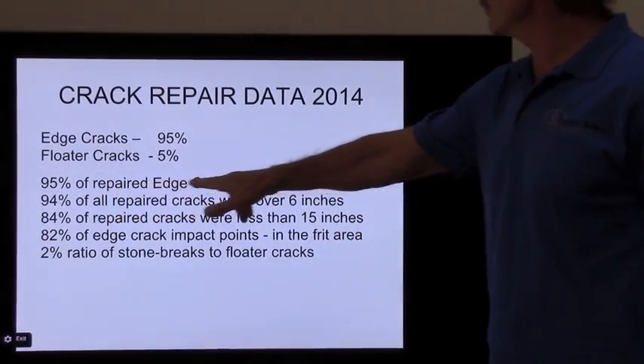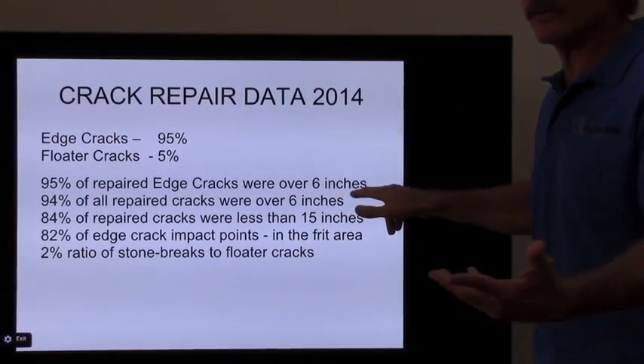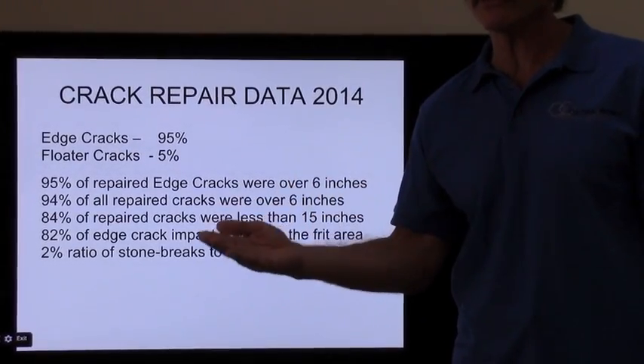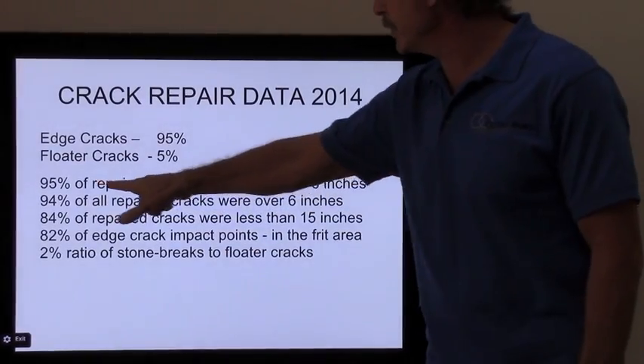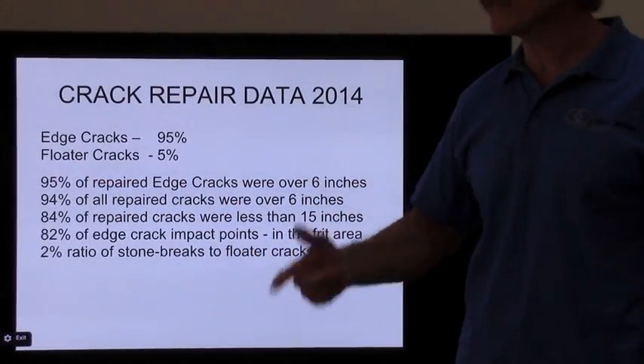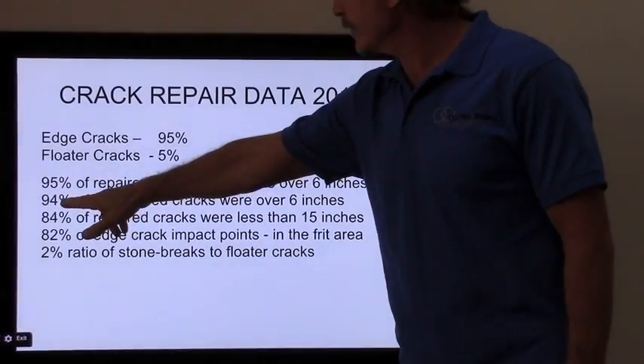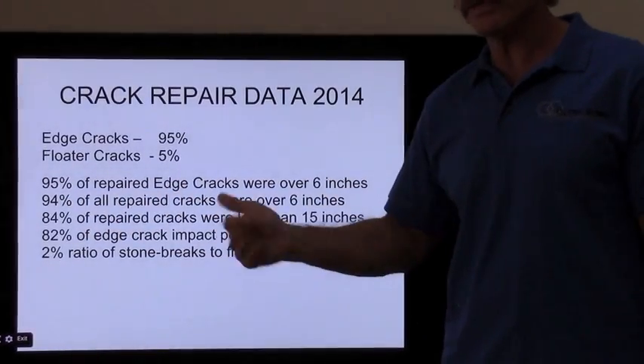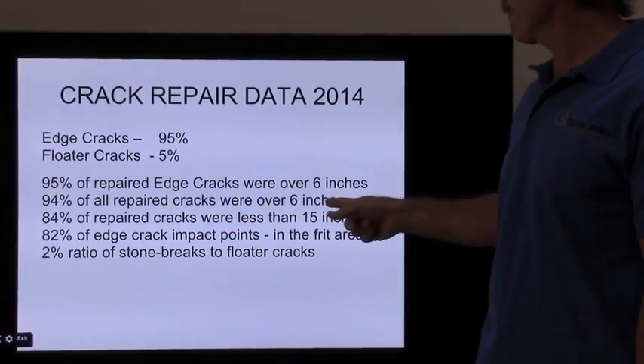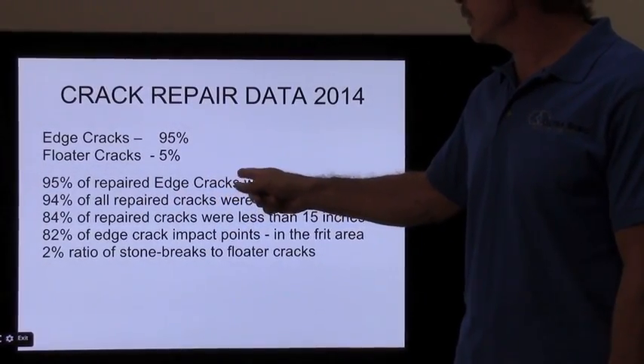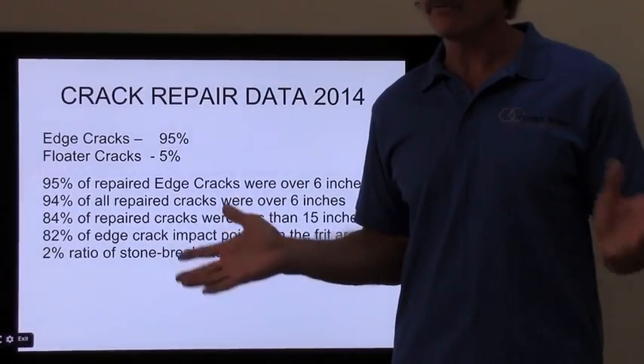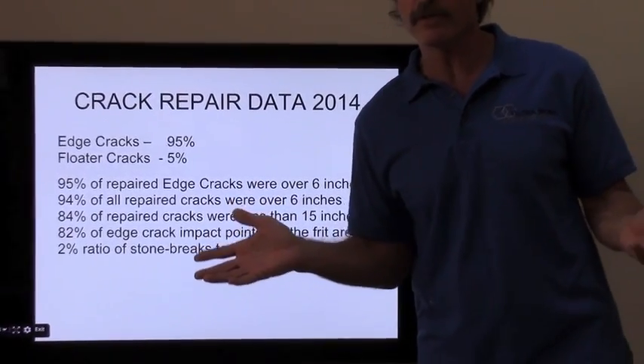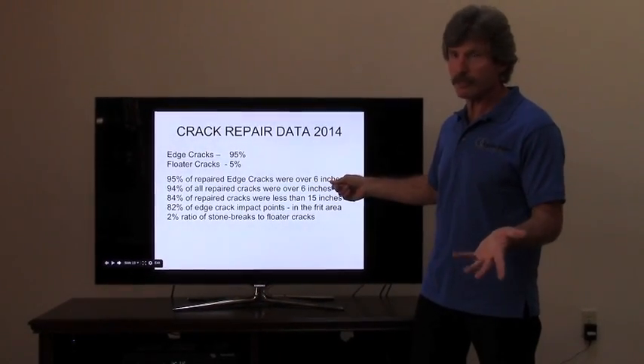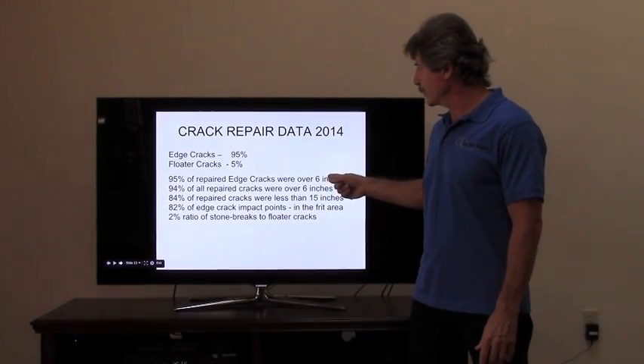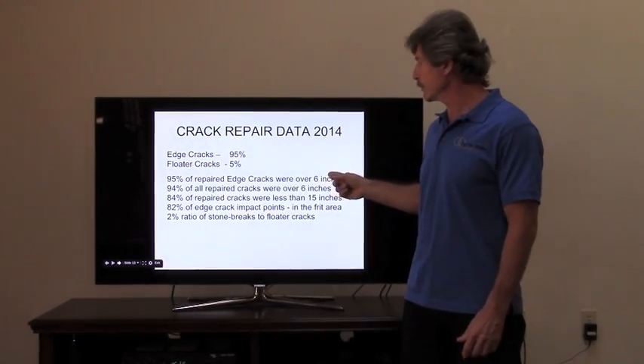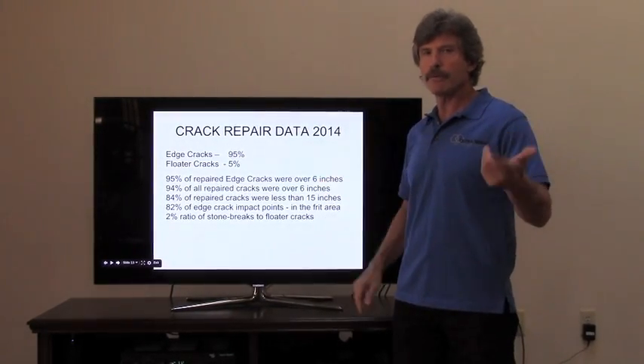Well, 95% of repaired edge cracks were over 6 inches. Why is that? That's because of that induced installation stress. That stress causes an edge crack to go over 6 inches 95% of the time. In fact, 94% of all repaired cracks, this is floaters and edge cracks, were over 6 inches long. Now, you might hear insurance companies and third-party administrators and windshield manufacturers telling consumers you can't fix it if it's longer than a dollar bill, which happens to be 6 inches. Well, that's called deceptive trade practices. They're deceiving the consumer and telling them that something that is repairable is not.